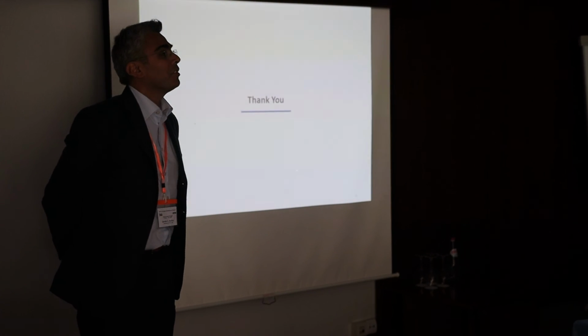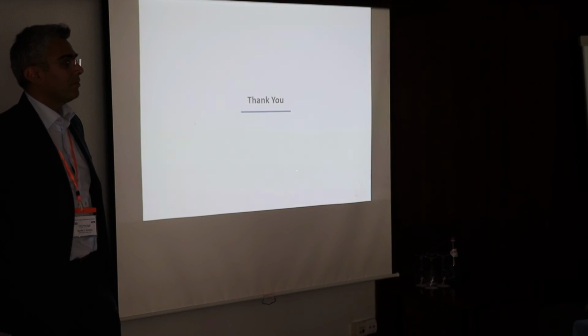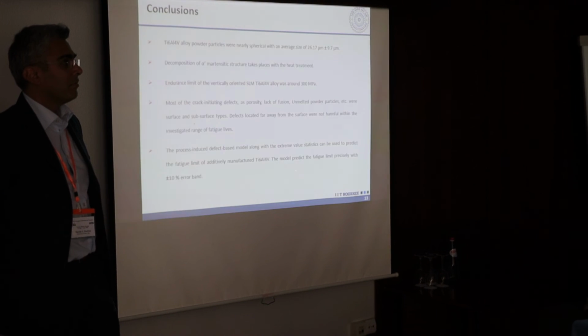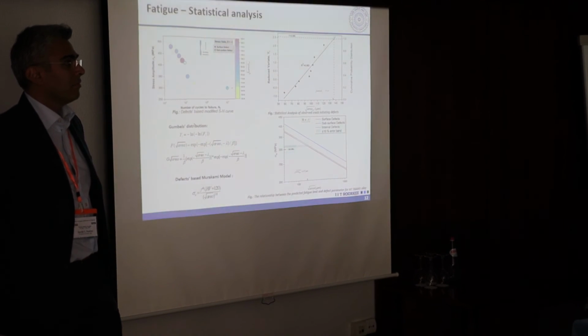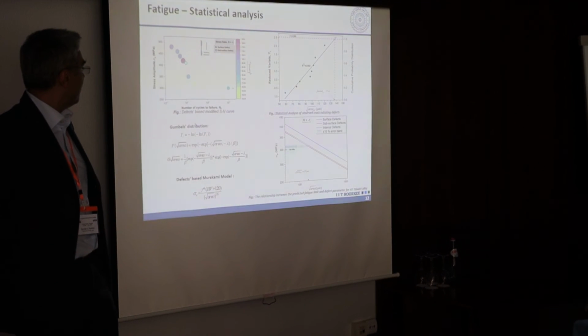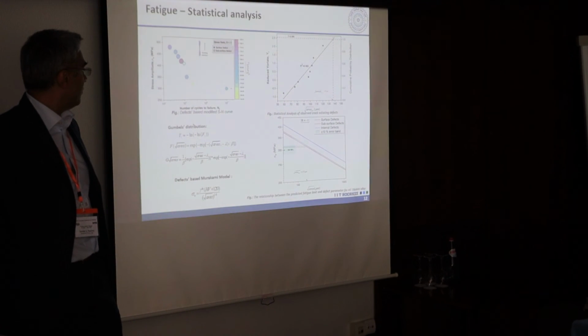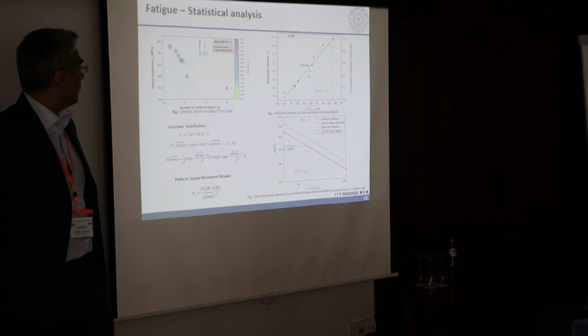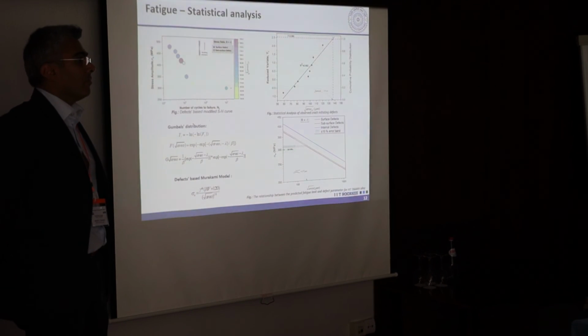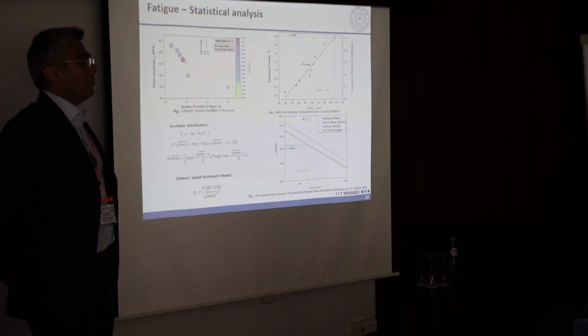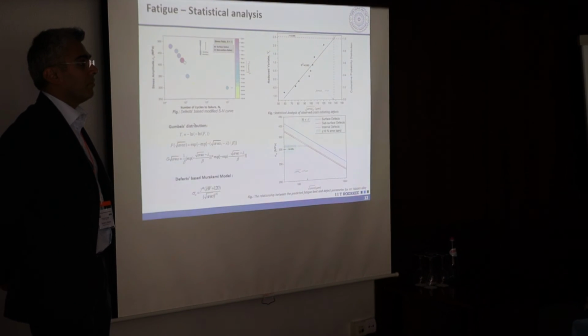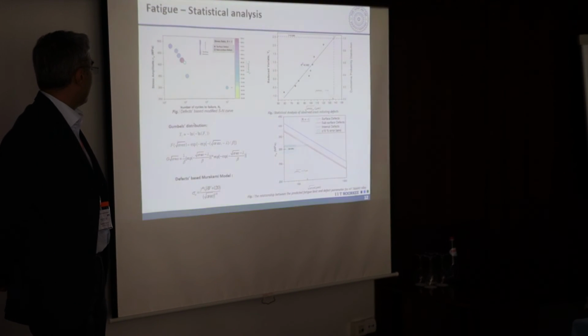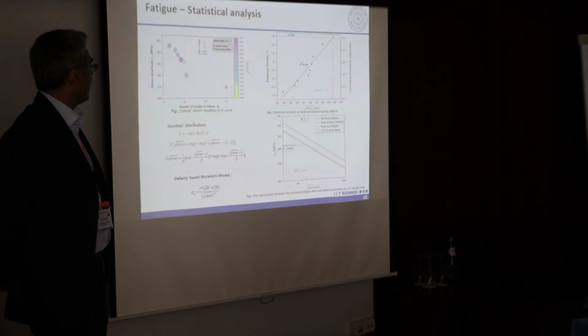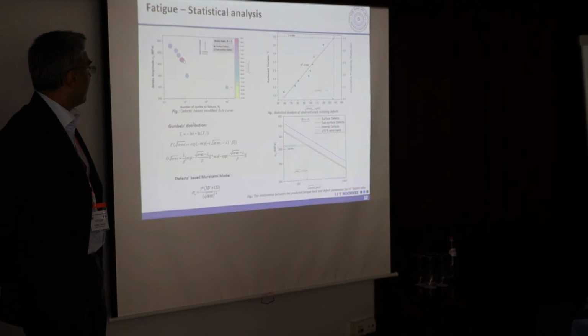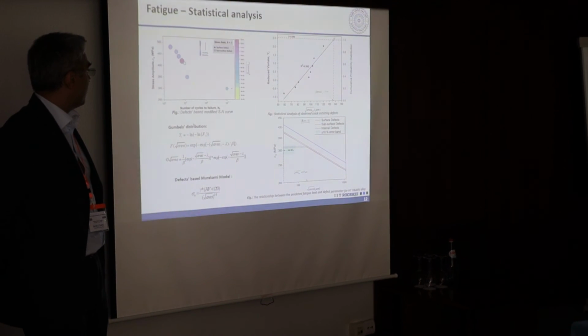You showed some Murakami prediction lines. How do you make sure that they are good enough, that the accuracy is okay for your material? Actually, we have used the material parameter here, hardness and the location of the defect. Yeah, but still, hardness is like an assumption. The Murakami model is very strong and can relate the location of the defect and area. Yes, there are some more parameters to evaluate, but in our case, we have used this same model where the predicted life has been correlated with the hardness.